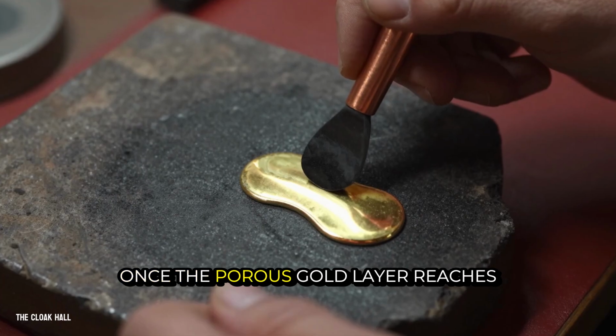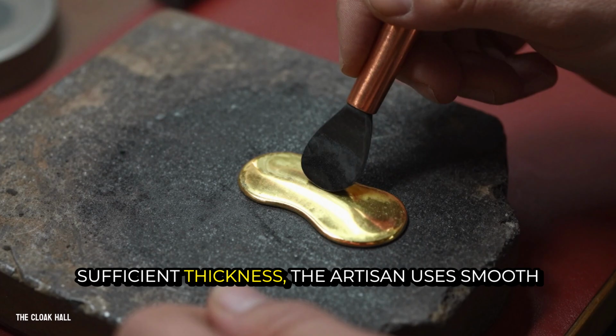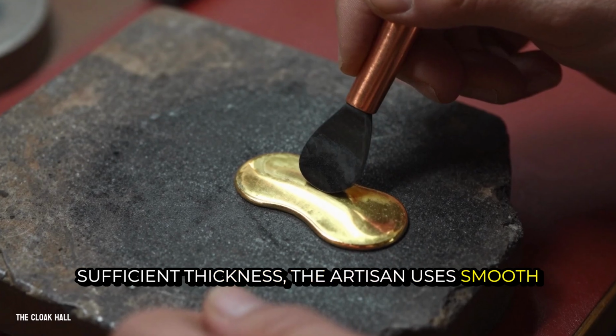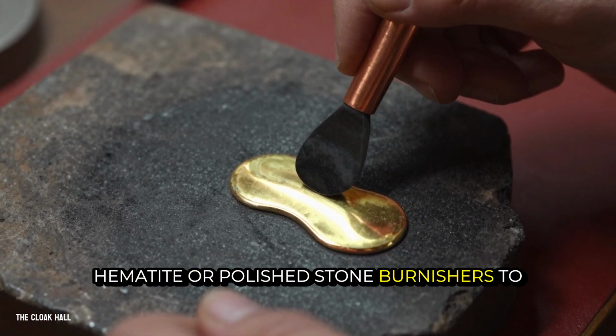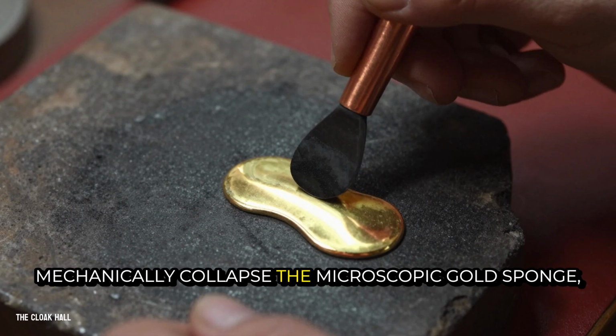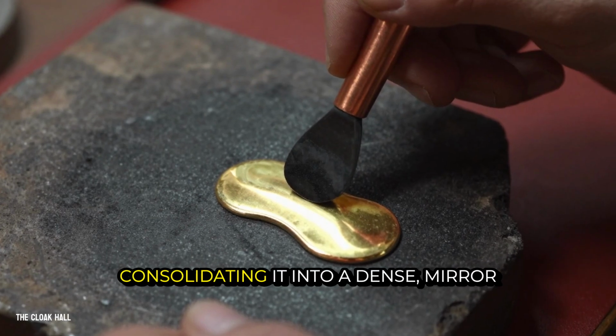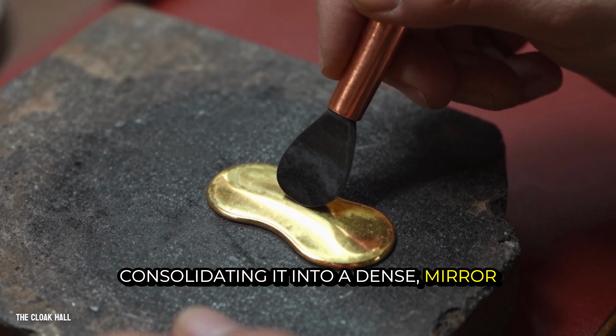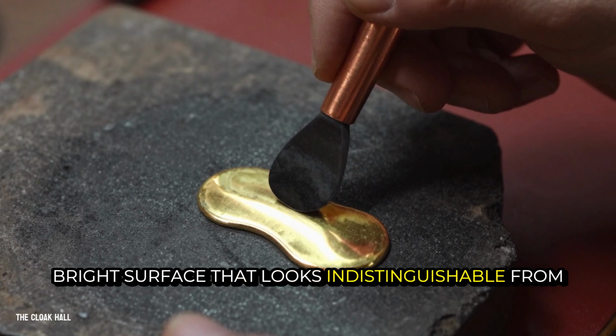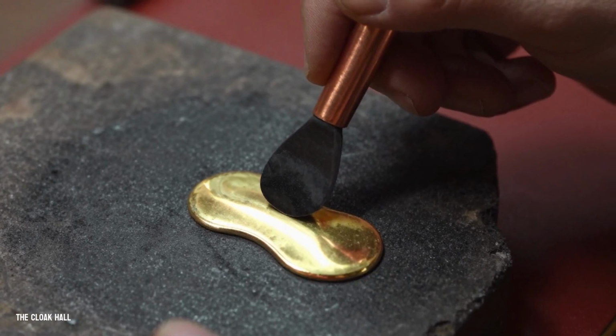Once the porous gold layer reaches sufficient thickness, the artisan uses smooth hematite or polished stone burnishers to mechanically collapse the microscopic gold sponge, consolidating it into a dense, mirror-bright surface that looks indistinguishable from solid gold bullion.